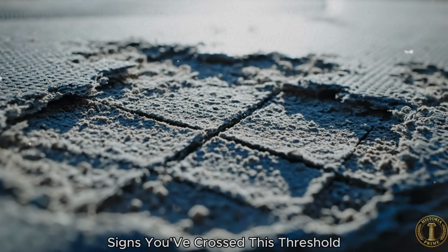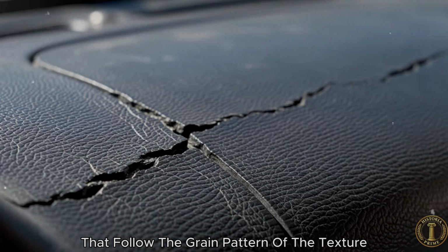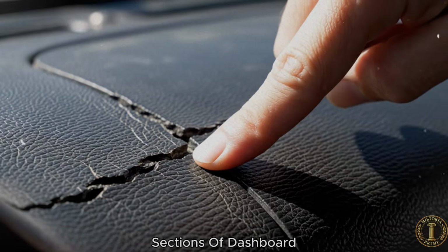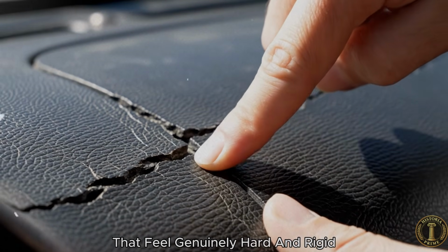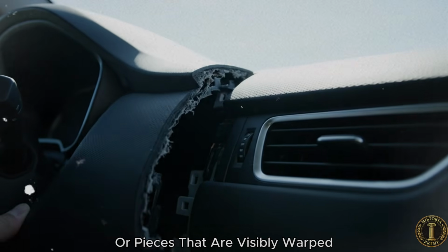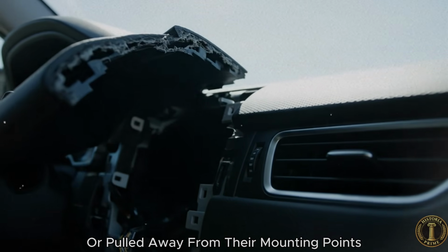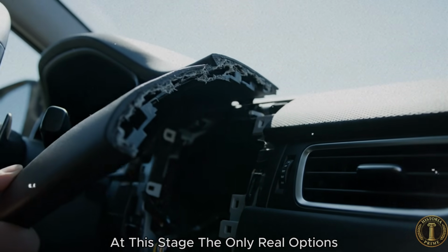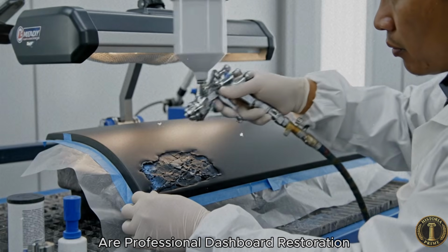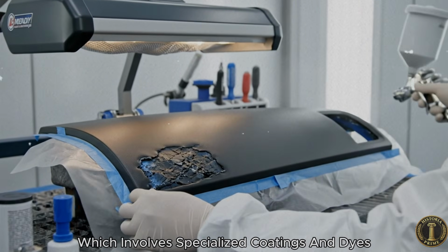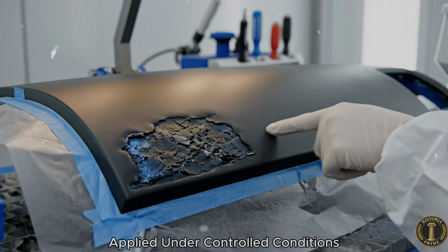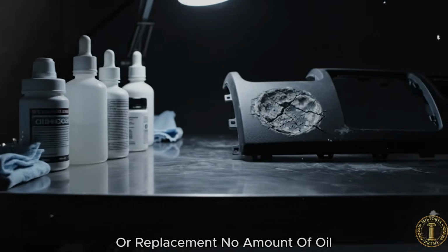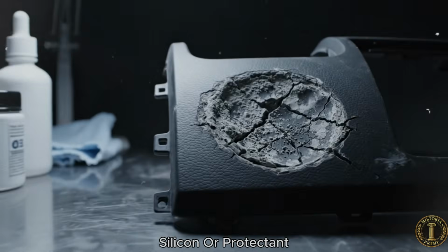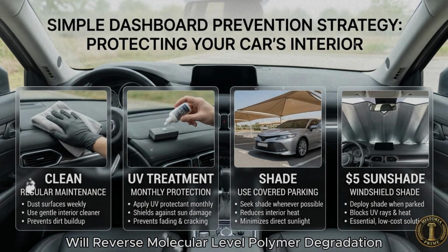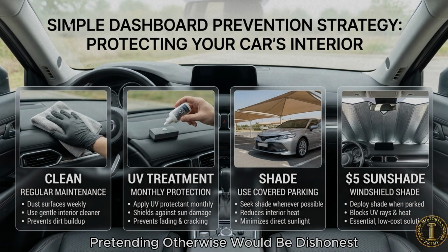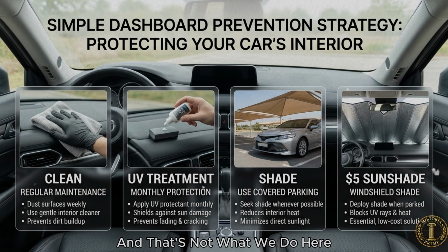Signs you've crossed this threshold: deep cracks that follow the grain pattern of the texture, sections of dashboard that feel genuinely hard and rigid rather than slightly yielding, or pieces that are visibly warped or pulled away from their mounting points. At this stage, the only real options are professional dashboard restoration, which involves specialized coatings and dyes applied under controlled conditions, or replacement. No amount of oil, silicone, or protectant will reverse molecular-level polymer degradation. Pretending otherwise would be dishonest, and that's not what we do here.